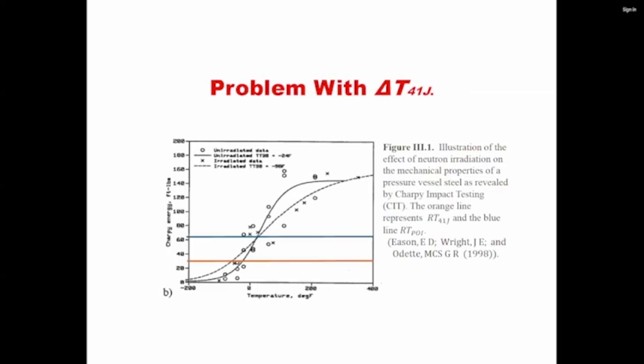On the other hand, if you were to find the shift at the point of inflection of this symmetric hyperbolic tangent function, you can see there's very little effect. And one of the issues here is that we're not absolutely certain what level of irradiation was applied to this sample. Next slide, please.